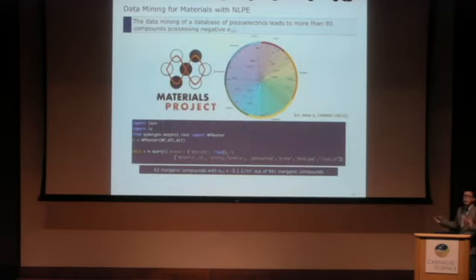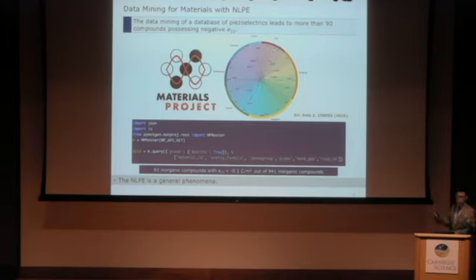Then the question is how many compounds we can find. The good thing is, back in 2015, there was already a first-principles-based database of piezoelectrics with their e33 calculated with density functional perturbation theory. This is open source, well-curated data we can access from Materials Project. This database contains nearly 1,000 inorganic compounds. So with just two lines, we quickly identify nearly 100 inorganic crystalline compounds with e33 smaller than -0.1 coulomb per meter squared. So this really demonstrates that this phenomenon is much more common than we thought.